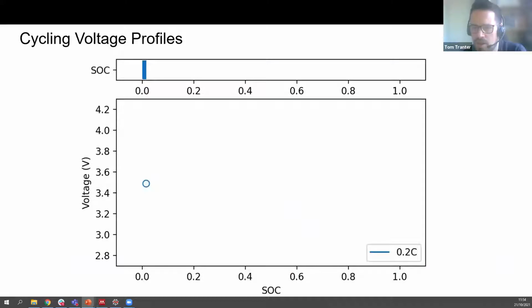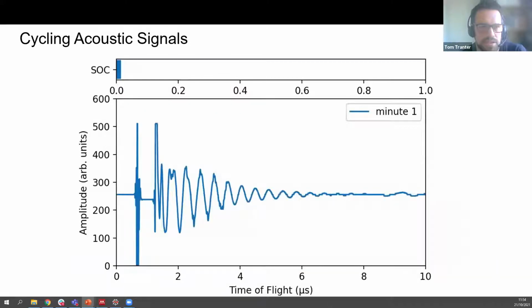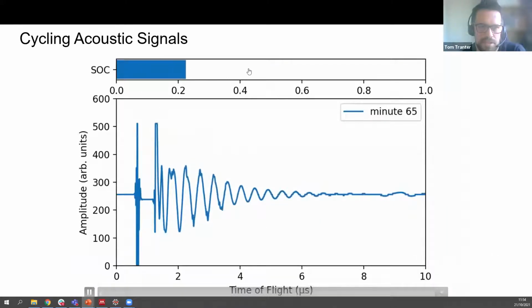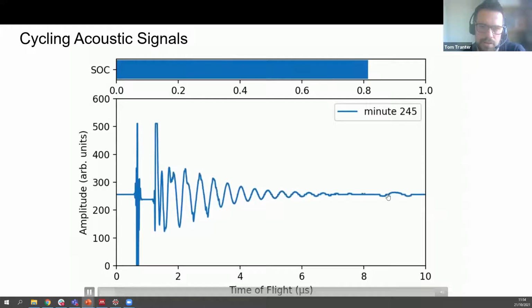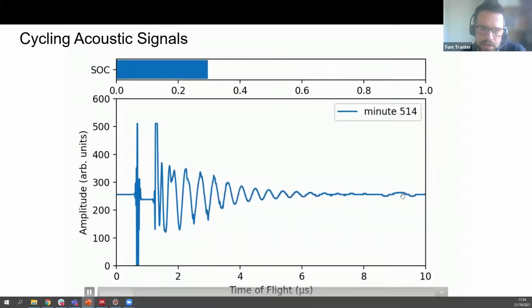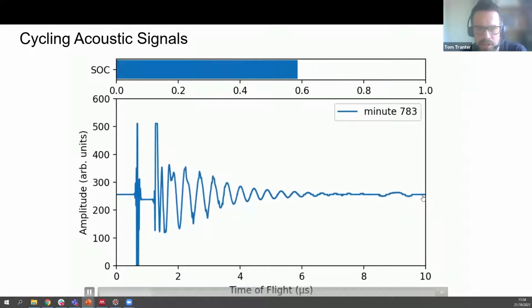I'm not going to have time now to show these videos, but this is essentially the raw acoustic signal over time. So this is charging and discharging at slow rates, and you can see it wobbles. It's this peak, this final echo peak it's referred to, which is the signal going all the way through, hitting the back of the cell and coming back. When you're doing the analysis by hand, we're just picking that one peak and looking at the shift in time of flight there. With the machine learning, we can take the whole waveform as our feature input, and we can get information about the whole cell essentially.